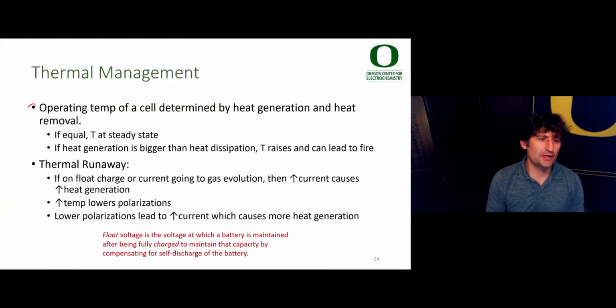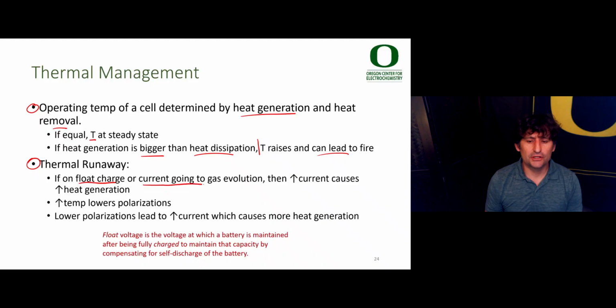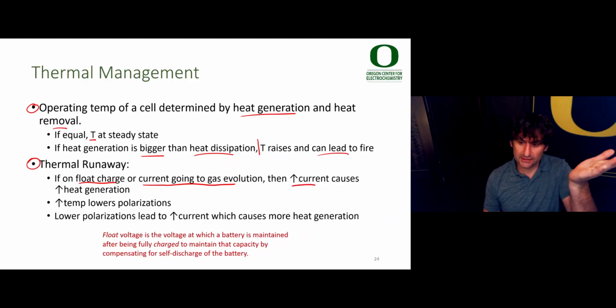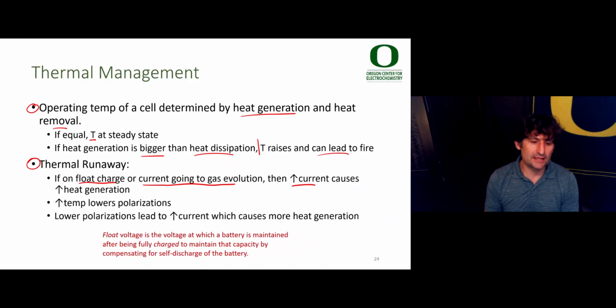So of course the operating temperature of the cell is determined by both heat generation and heat removal. If they're equal, temperature comes to a steady state. If one is bigger than the other, for example, heat generation is bigger than heat dissipation, then the temperature slowly rises with time, and this can lead to a fire. Call this thermal runaway. In one example, if you're on float charge, say at a constant voltage, or some of your current is going to gas evolution, as the current passes, it causes the temperature to rise, which increases the amount of current that flows at a given applied float potential.